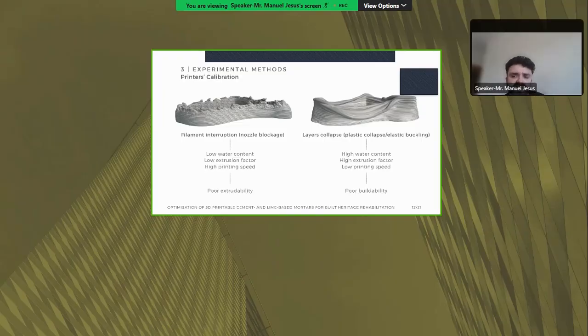Before the final prints were initiated, the printing parameters were calibrated during preliminary testing. The first priority here was to optimize extrudability, achieved by balancing the printing speed and the extrusion factor. As shown in the figure on the left, interruptions in the filament resulted from nozzle clogging. These failures were attributed to an insufficient extrusion factor, excessive printing speed, or even a lack of water in the mortar, which prevented consistent material flow.